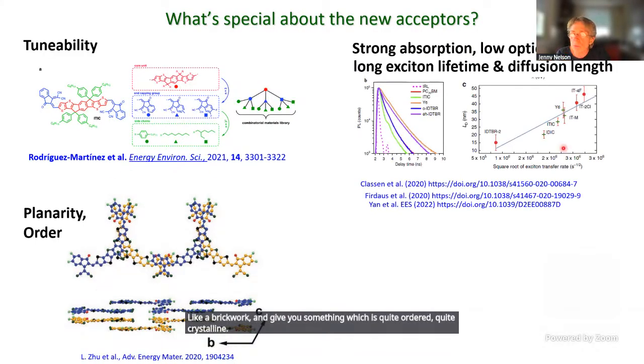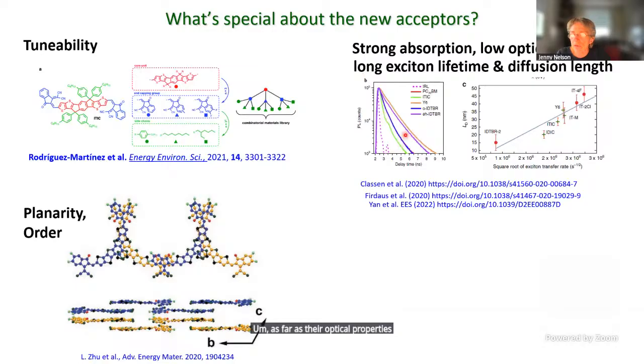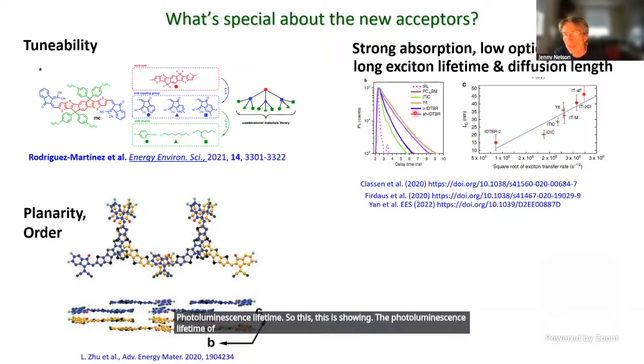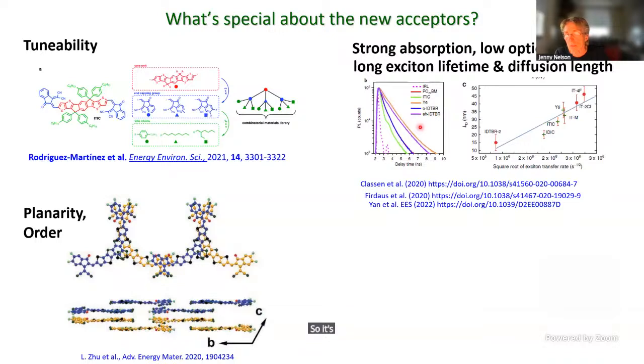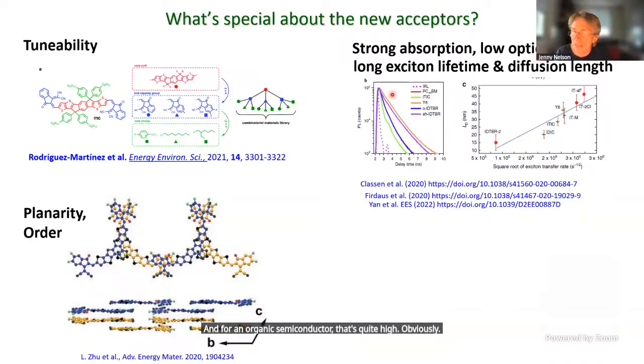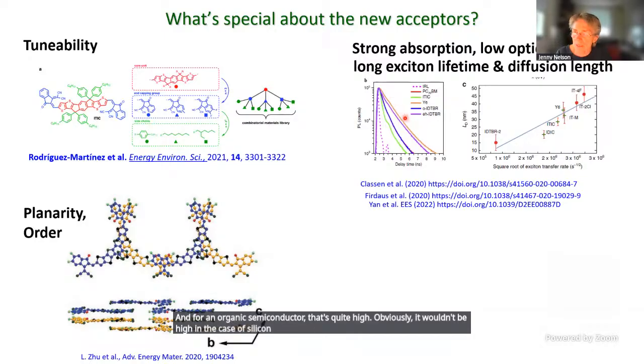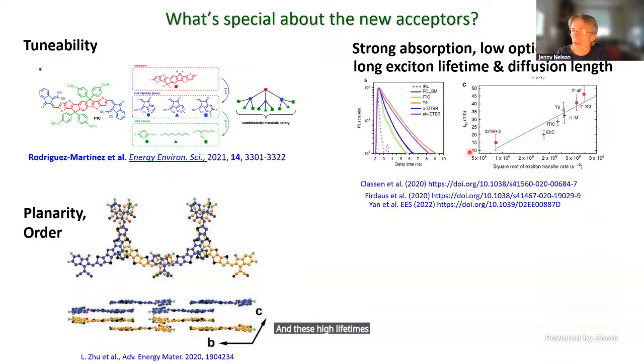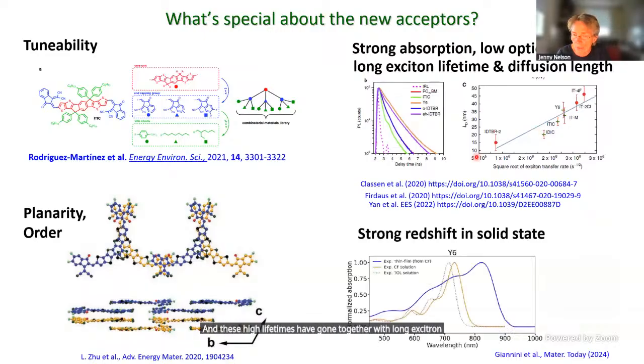As far as their optical properties go, they have quite long photoluminescence lifetime. So this is showing the photoluminescence lifetime of Y6. So it's got a lifetime of order of magnitude of nanoseconds. And for an organic semiconductor, that's quite high. Obviously, it wouldn't be high in the case of silicon, but for an organic semiconductor, it's pretty good. And these high lifetimes have gone together with long exciton diffusion length.